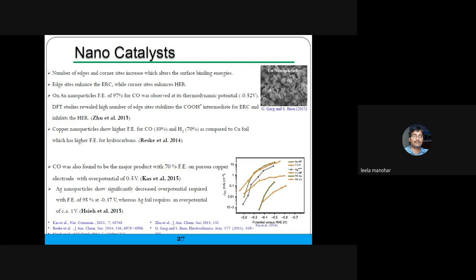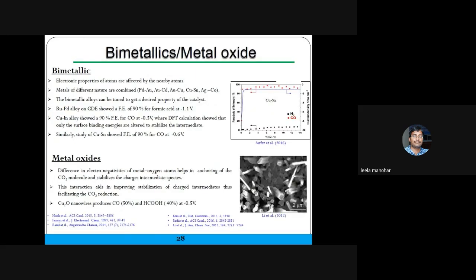There are so many kinds of studies they have done on catalysts. They also have different literature on bimetallics and metal oxides. In the bimetallics, they're also getting a very good efficiency of 90% for formic acid, and stability studies have also been done, showing very prominent results. And the metal oxides have also shown very good results for formic acid as well as CO.